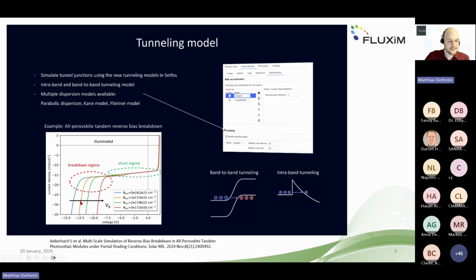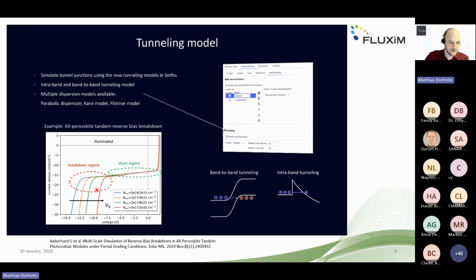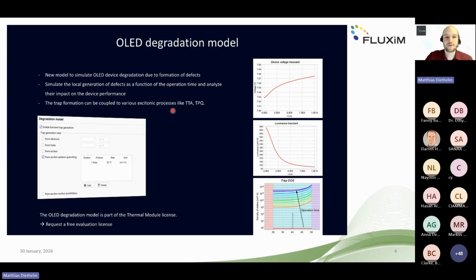To understand this breakdown, as you can see here on the bottom left of a solar cell, we looked into this in a project with a recent publication of a colleague of mine. You need to understand the tunneling, or you need to have a tunneling model inside, to get this breakdown, which is partly due to the strong fields you have at the interface, which means they are also influenced, as you can see in this graph, by ion density, which modifies the electric field. So first I will introduce the degradation model, and it's even labeled here OLED degradation model, since a big part of introducing this model is coming from the OLED field.